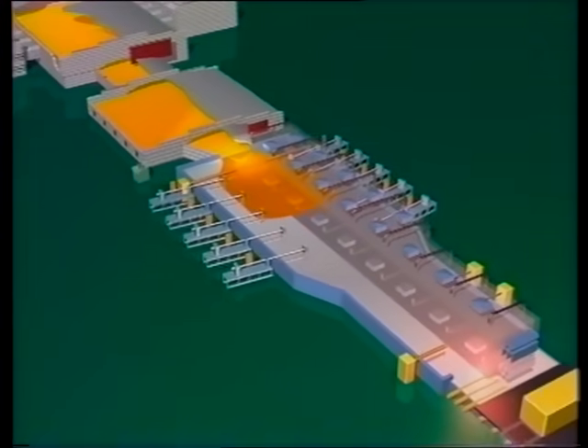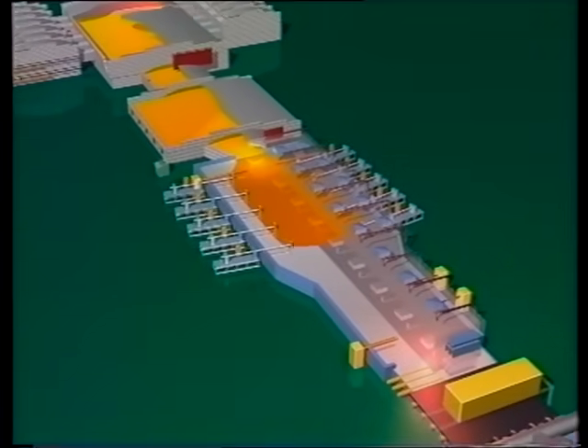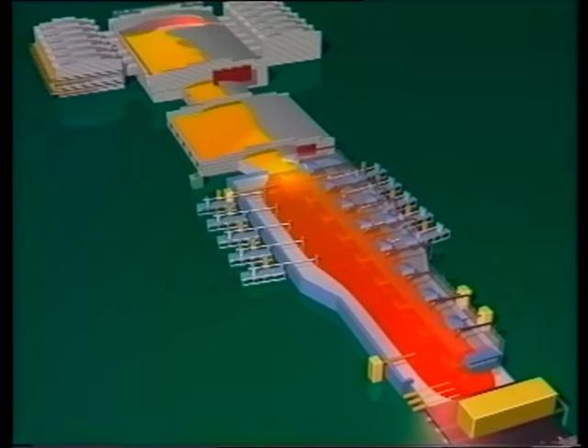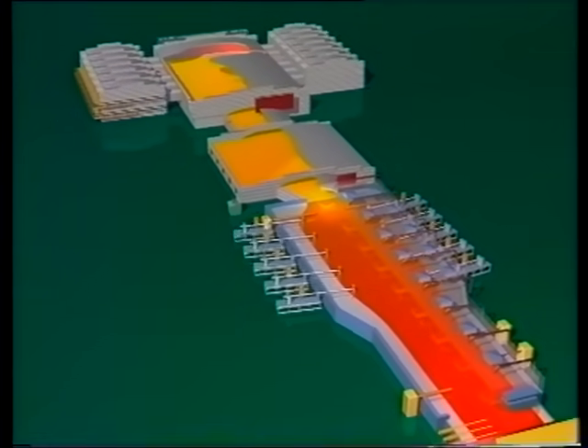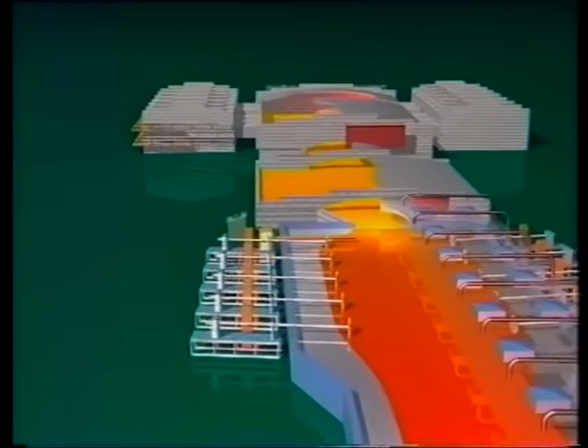Here the glass spreads out, following the perfect flatness of the tin, so that the upper and lower surfaces of the glass remain absolutely flat and parallel. The glass is made thicker by confining its initial outward spread over the tin. To make thinner glass, the top rollers controlling the width of the glass are speeded up to produce a gentle stretching action.